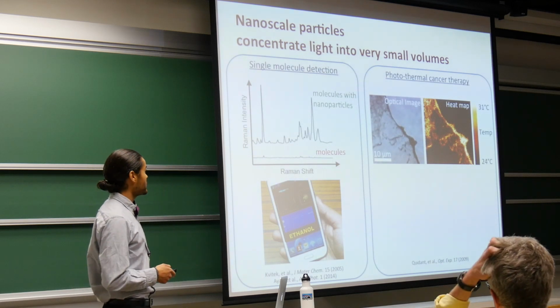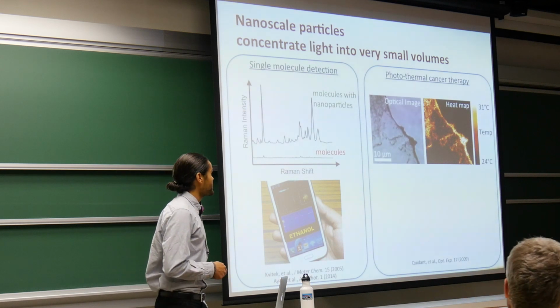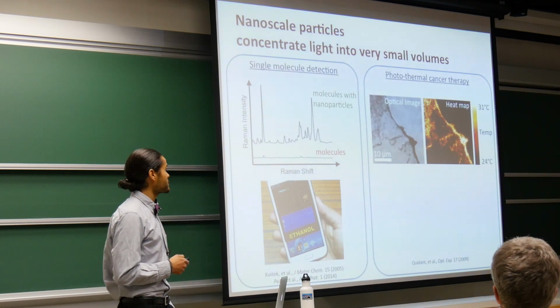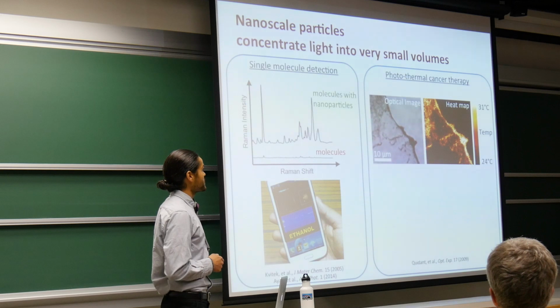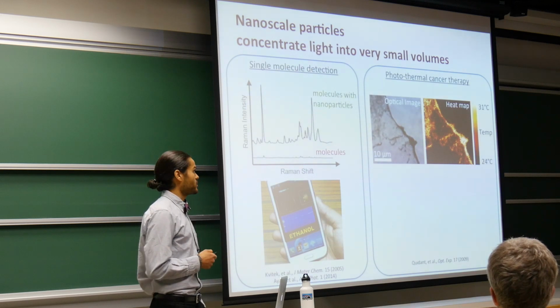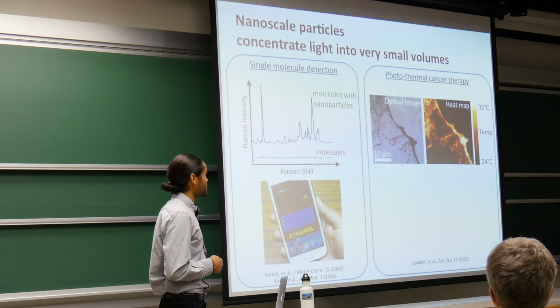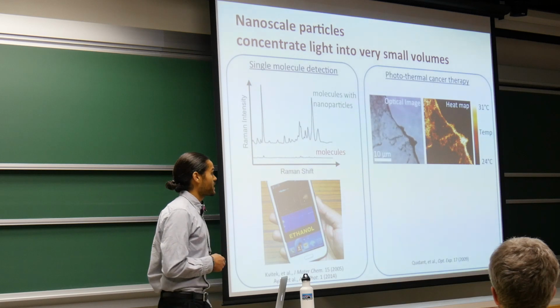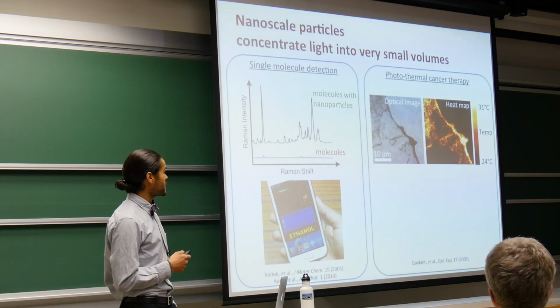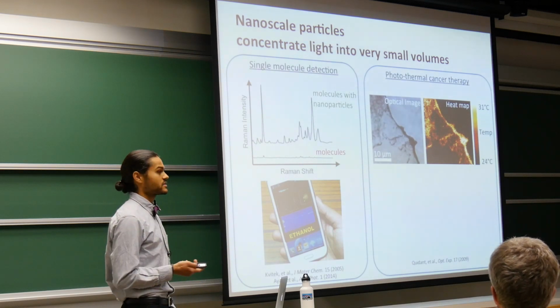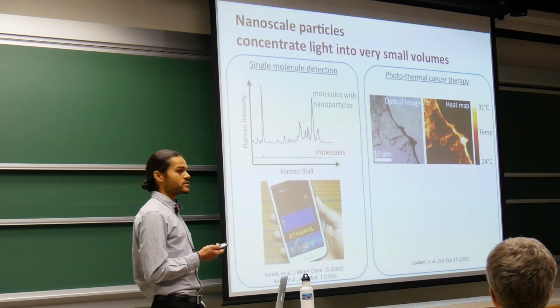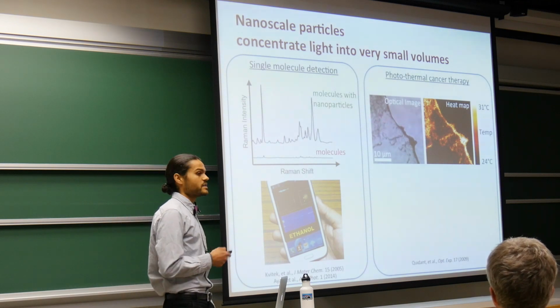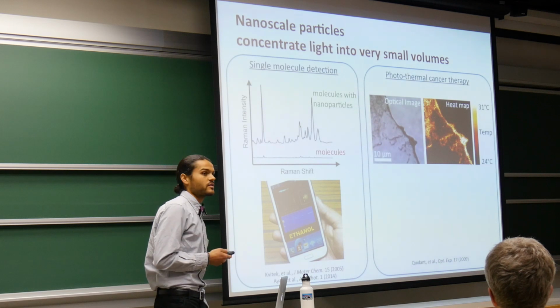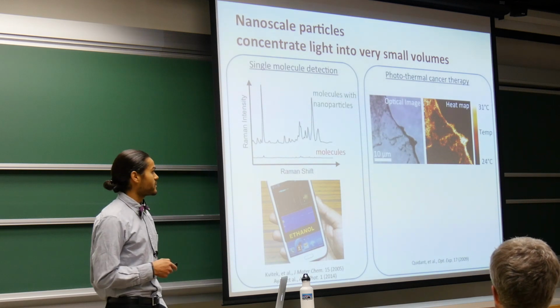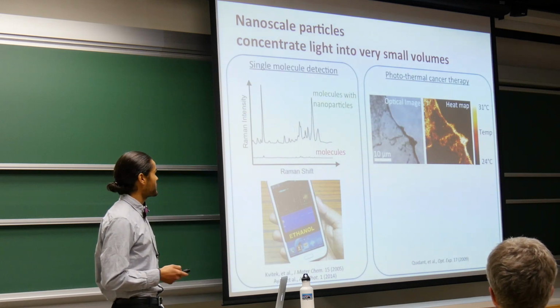So here on the left, we see an optical image of gold nanoparticles dispersed on a glass slide, where the dark portions of the optical image correspond to higher concentrations of these nanoparticles. Using a technique called fluorescence polarization anisotropy, these researchers were able to actually probe the local temperature near these nanoparticles and found that the temperature increased by about 7 degrees for the highly concentrated areas of the sample.